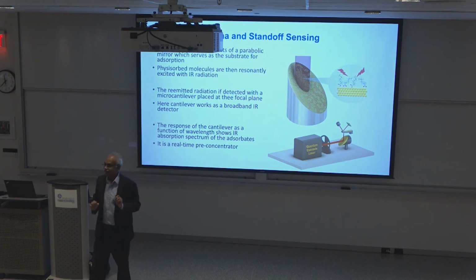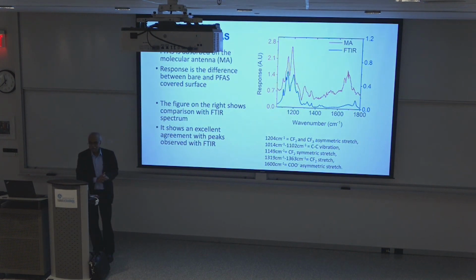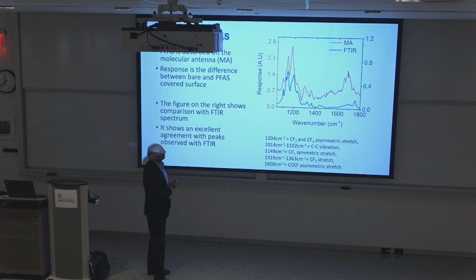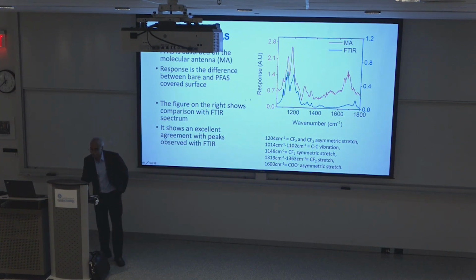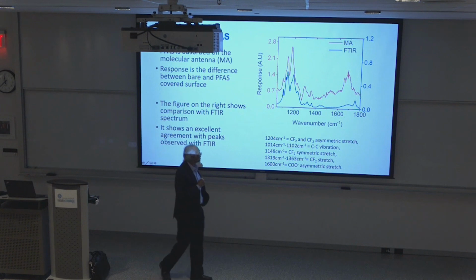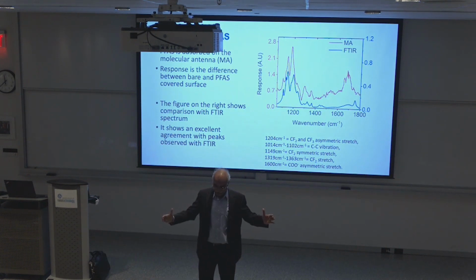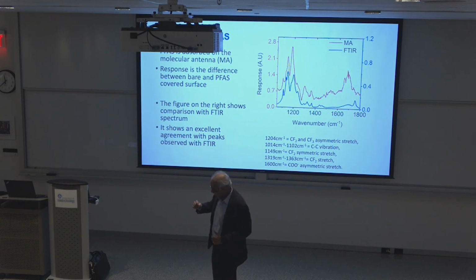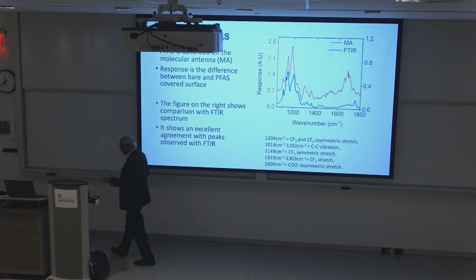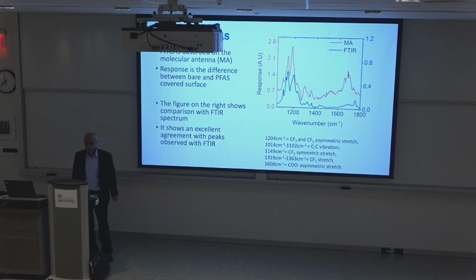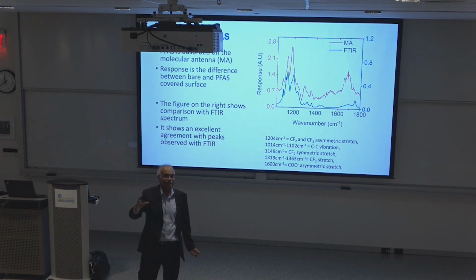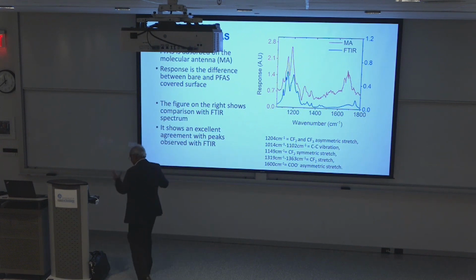So we said, okay, let's test it out. And here we go again, PFAS absorbed on the surface. And then you can see this is the cantilever response here. And this is the wave number, and you can detect all the different molecular vibrations. So basically, you are increasing the area of the sensor indirectly, and so even if the concentration is extremely small, you can still detect it. We have shown with this approach we can detect parts per trillion level molecules right away, in real time. You don't need a pre-concentrator because the pre-concentrator is built into the system itself.